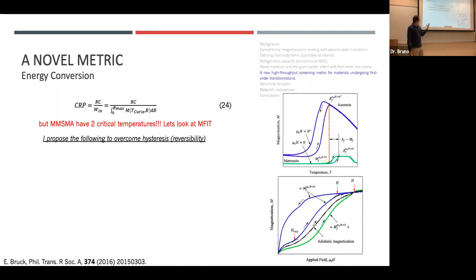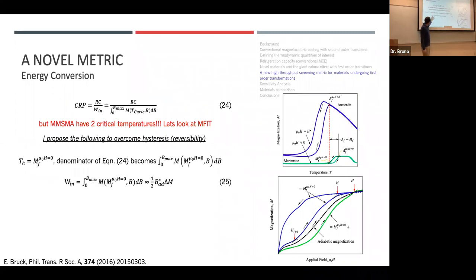So I propose to do the following to overcome the issues with hysteresis and minimum field levels to use these materials. First, we need to describe our hot temperature reservoir of our cycle at our Mf temperature. And our integral for work input needs to be at that Mf temperature. We can define work in as the integral of M dB, where B is the applied field. Here we have our magnetization versus applied field. Just looking at this diagram, this is a big assumption that I make, that we can approximate the energy as a triangle.